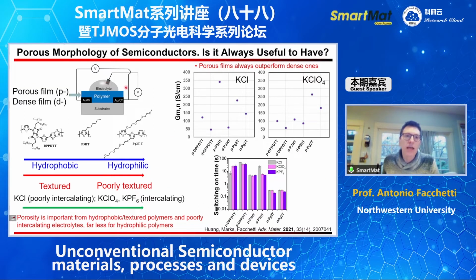And then we made the devices. Again, I want to remind you of the question we ask ourselves: is porosity important or not? So we made devices using the porous film and the dense film. We have 6 types of devices, because we have 3 polymers. As I said, this polymer is much more hydrophobic, and this is much more hydrophilic. These 2 polymers are much more textured, while this one is much less textured. And then we use 3 types of electrolyte. KCl, where the chloride is a very hard anion, so it intercalates very, very poorly. The other 2 electrolytes intercalate much more efficiently.